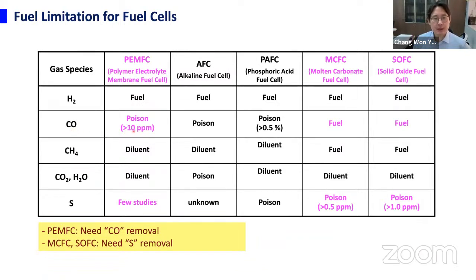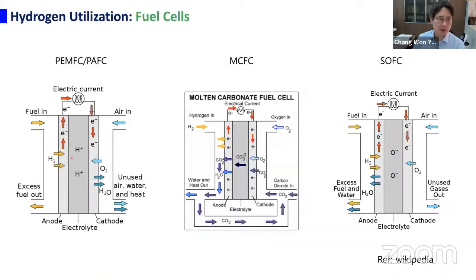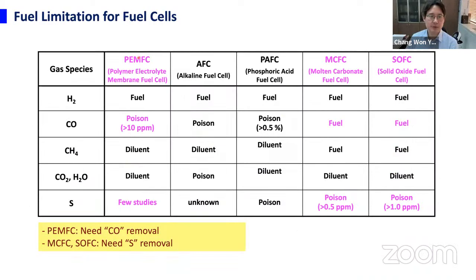In the case of CO, CO can't really be an appropriate fuel for PEMFC because the electrode material here is platinum. Actually, platinum is located at this anode here. And if CO goes in, the CO strongly binds with the platinum and deactivates the whole process. So CO must be removed for PEMFC. This CO is a poison, not a fuel. Over 10 ppm poisons the PEMFC, but nowadays we say less than 1 ppm of carbon monoxide must be supplied into PEMFC.